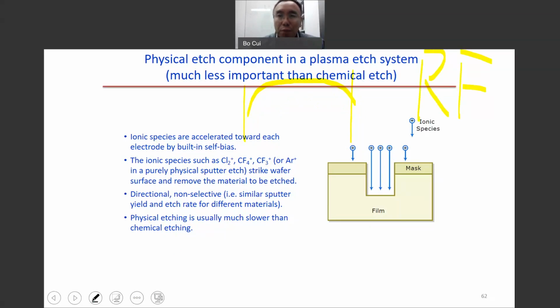So for the RF plasma, there is no DC voltage. But because of the property of the plasma being positively charged, there will be a voltage drop along both electrodes. This voltage drop will accelerate the ions to bombard the surface. So this gives the physical etching of the material. Obviously, this etching is very directional, but the etching rate is slower because of the lower concentration of ions compared to the free radicals.